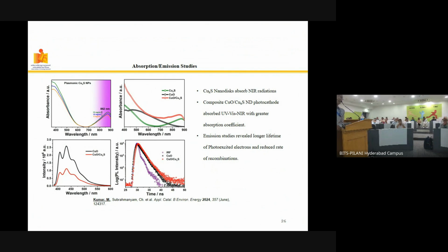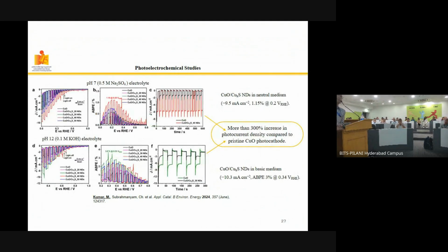You can see that it has a good absorption in the visible region. And for example, you can also look at that the excited lifetime is relatively longer. You can also look at that it has a good absorbance, especially in this region I'm referring to, because in the previous cases you only concentrated on these regions, but now once you have made some kind of a rod, the NIR starts active for this catalyst, and that's where you start seeing that this is active in this case. So that's the combination which we looked at.